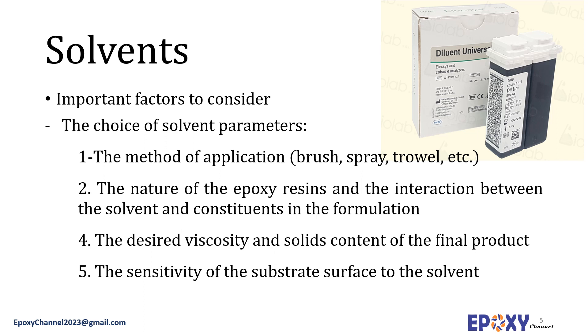Once the adhesive is applied, the solvent must evaporate prior to cure; otherwise bubbles or vapor pockets could form, causing a physically weak joint with poor adhesion. The solvent in the adhesive formulation must not adversely affect the substrate — plastics, elastomers, and polymeric foams are especially sensitive to certain solvents used in epoxy adhesives. The choice of solvent will primarily depend on the method of application (brush, spray, trowel, etc.), the nature of the epoxy resins, the desired viscosity and solids content of the final product, and the sensitivity of the substrate surface to the solvent.